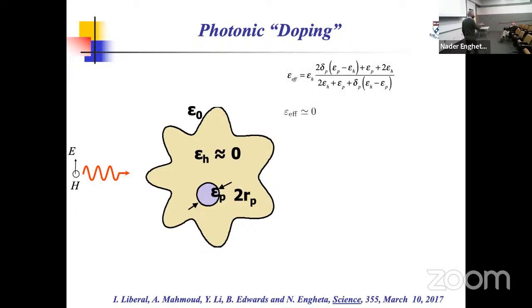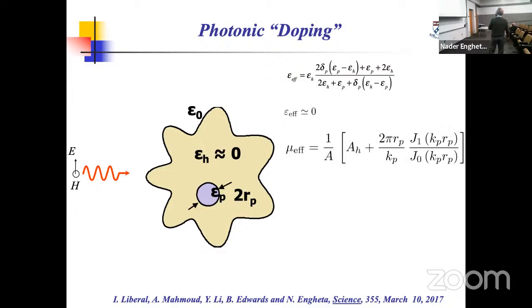It turns out that if you start with epsilon near zero and you put a dielectric rod in it, the regular epsilon, from the outside observer, this entire ensemble still has effective permittivity near zero. I can show you the proof of that after the talk, if you're interested. But if effective epsilon has not changed, what is it that has changed the scattering? Effective mu. This is quite interesting. In other words, we mathematically proved and experimentally showed that if you put a non-magnetic dielectric rod, mu equal to one, inside the non-magnetic ENZ region, mu equal to one but epsilon zero, from the outside observer this entire ensemble has epsilon near zero, but effective mu not necessarily one. So a combination of two non-magnetic materials gives you an effective mu different from one.